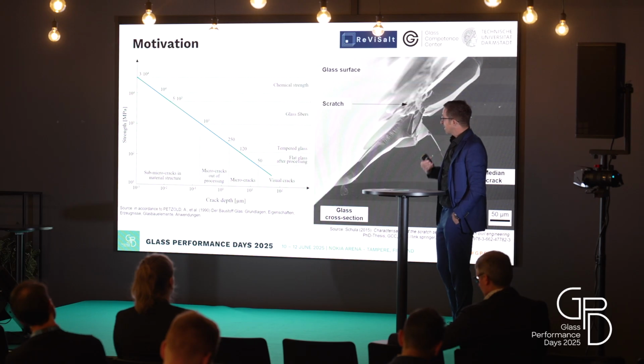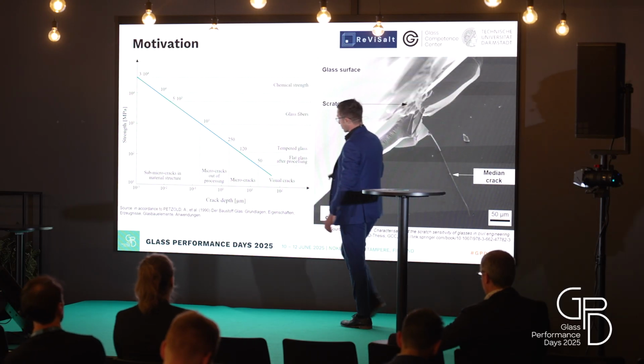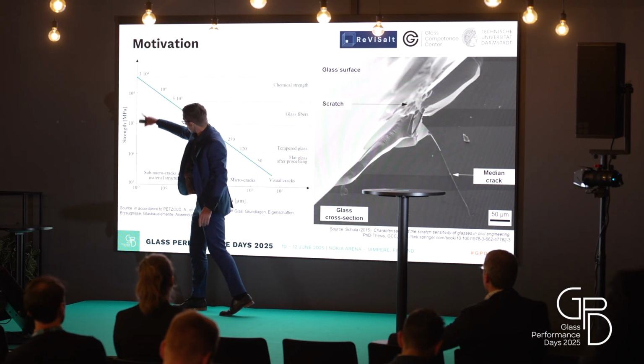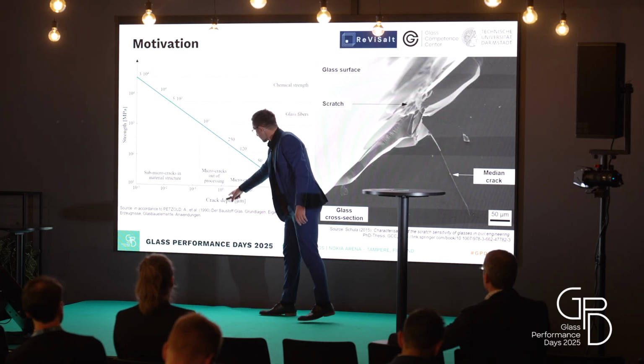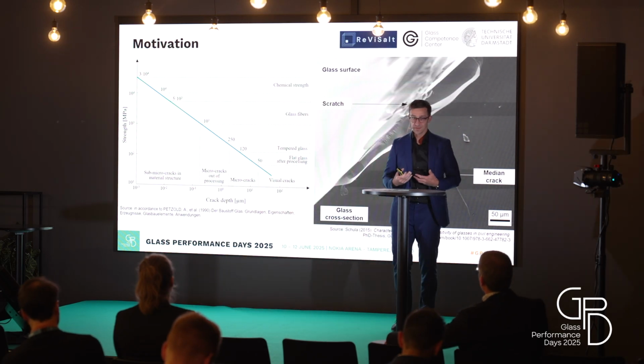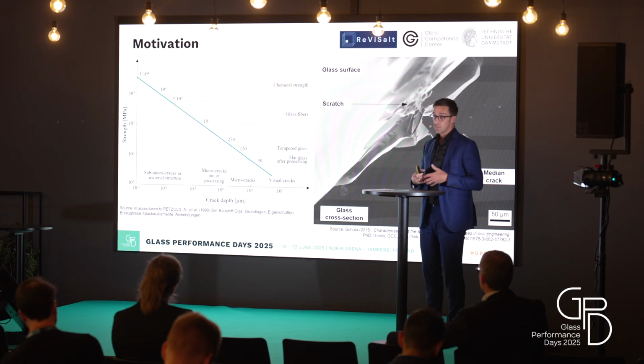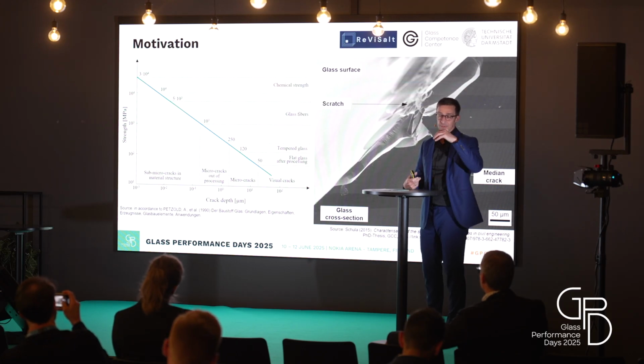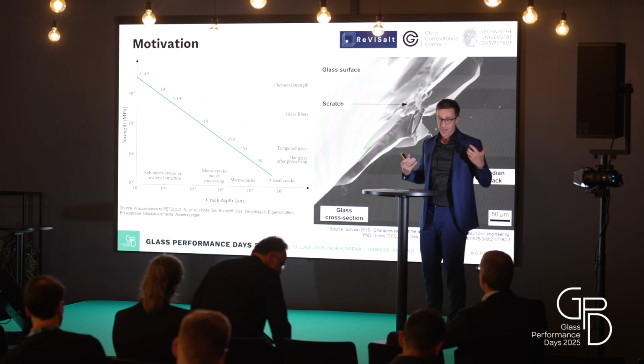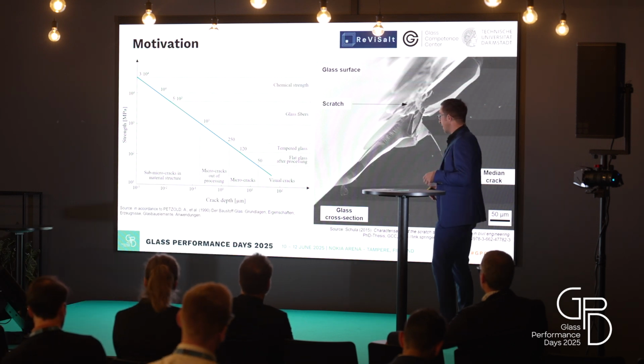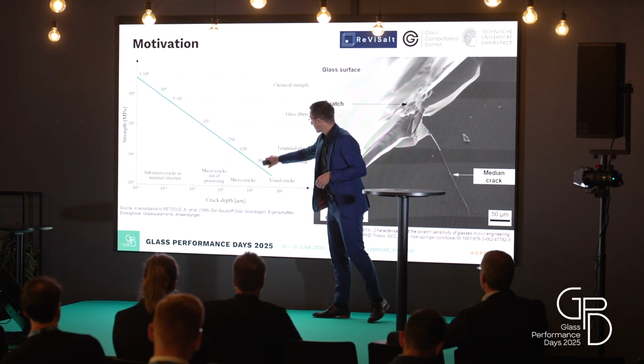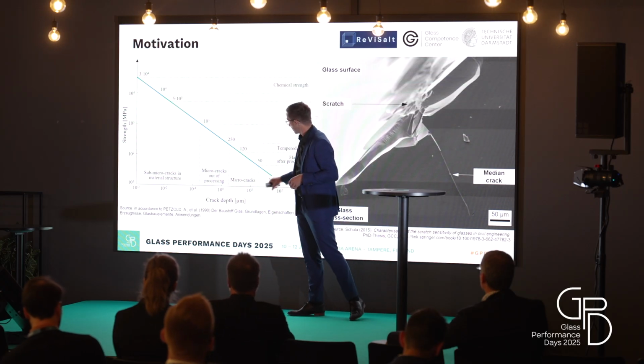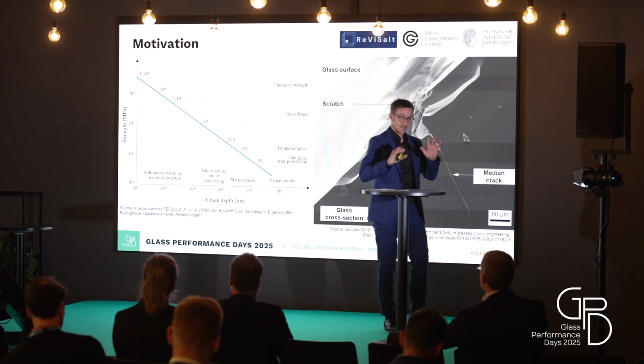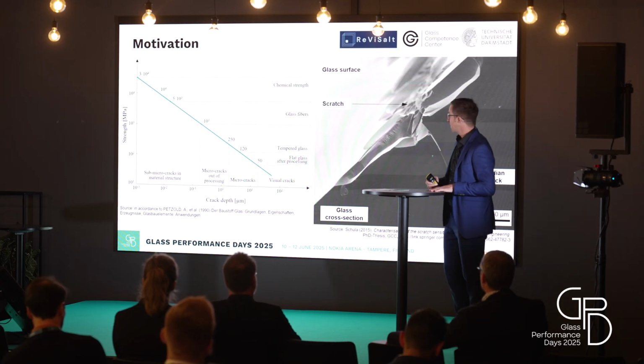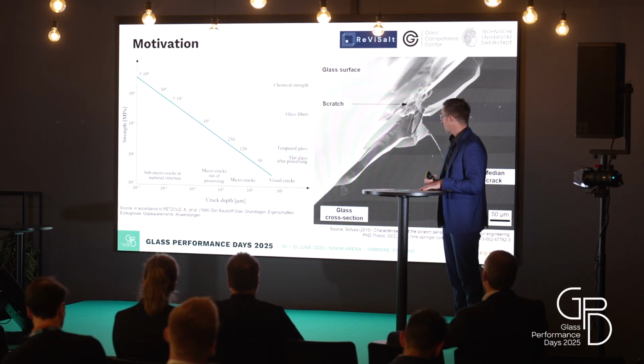And we know that here on this chart, this is the strength in megapascal. This is the crack depth. This is a function, more or less, here in log scale. And we know the internal strength of glass is in a region over 10,000 megapascal. But if we have cracks which are visible, we are more in a range here of 50. And this is the range, more or less, we deal with in architectural glass. Maximum, I would say, 150 for chemically tempered glass.